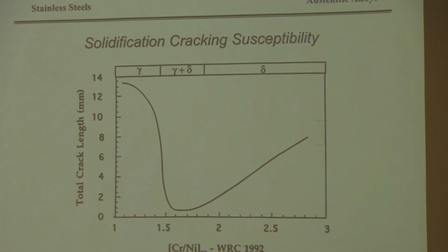This is a diagram that demonstrates solidification cracking susceptibility of austenitic alloys. This is total crack length, which basically is a measure of how much cracking you get. You add up all of the cracks and add it together, and that's your total crack length. This is a chromium-nickel equivalent relationship. This is where you would take those chromium and nickel equivalents that I showed you on the Schaeffler diagram, calculate those, and then divide the nickel equivalent into the chromium equivalent.